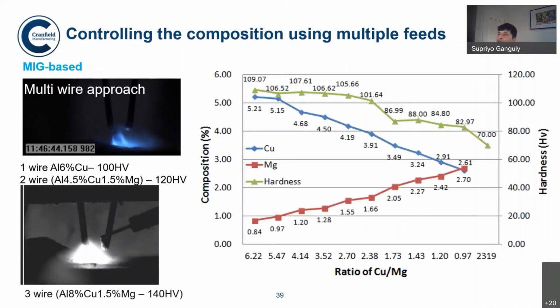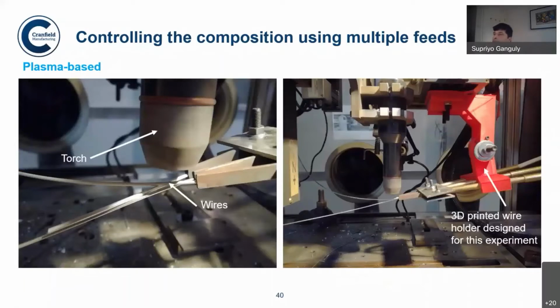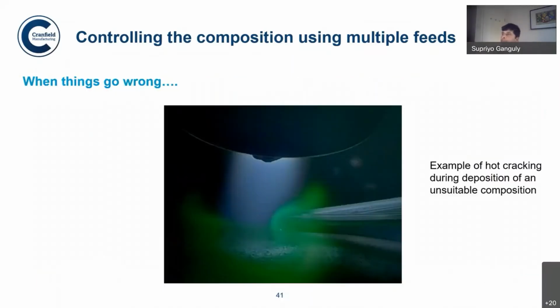So this particular work was then taken forward with the addition of a third wire, because in that case we can have a deposit which is as strong as probably the parent metal. That is one of the major issues in aluminium, that the weld metal and the associated heat affected area have quite low strength as compared to the main parent metal. And now this is being controlled by adding several wires, and this particular principle is taken for development of additively built aluminium parts. So you can see here